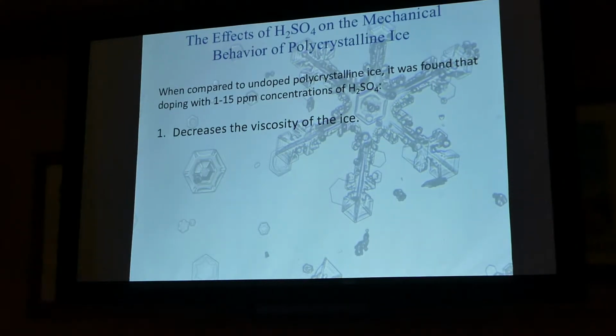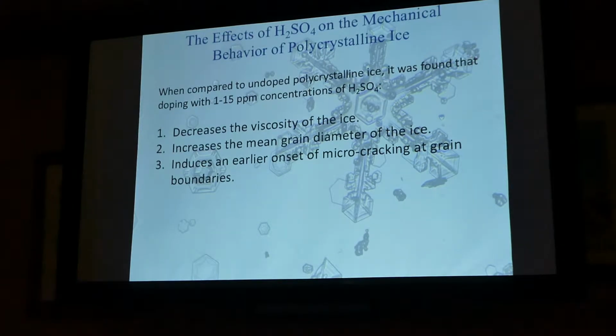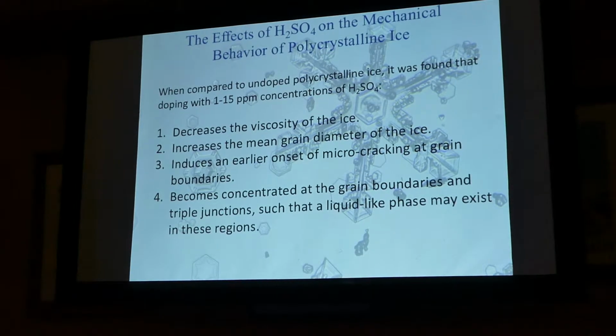So in conclusion, these are the conclusions just for the ice. We found that the sulfuric acid decreased the viscosity of the ice, increased the mean grain diameter, and induced an earlier onset of microcracking. It becomes concentrated at the grain boundaries and triple junctions, such that we'd see these liquid-like phases.